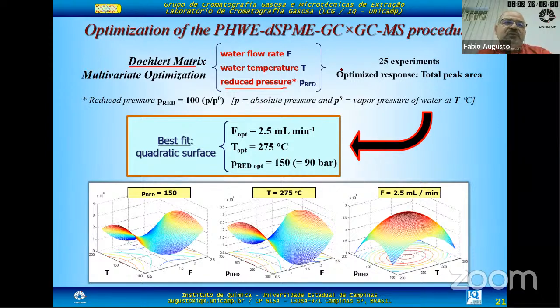We combine the conditions in 25 sets and run 25 experiments in different conditions. The response optimized is the total peak area, the sum of peak areas of all analytes. For the best conditions, we fit the response surface and check where the maximum of that surface is. The best fit was a quadratic surface, and we found the optimum water flow and temperature are 2.5 mL per minute and 275 degrees, and the optimum pressure is 150 times the vapor pressure of water, which is 90 bars under those conditions. These are the response surfaces for the variables. As you see, it's a very complex behavior.